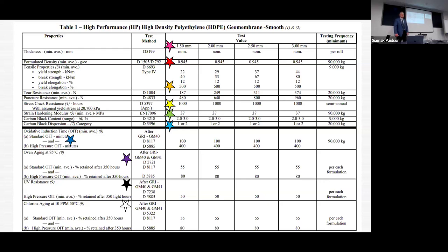You have to give up something, and one thing that you give up is the break elongation value. So that's only at 500%. Okay, that's not as long, not as big. Stress crack, it's up to 1,000 hours. Strain hardening modulus is at 37 megapascals. Okay, carbon black is 2 to 3%, but the carbon black dispersion is either category 1 or 2. There's no allowance for category 3. It's a better quality carbon.